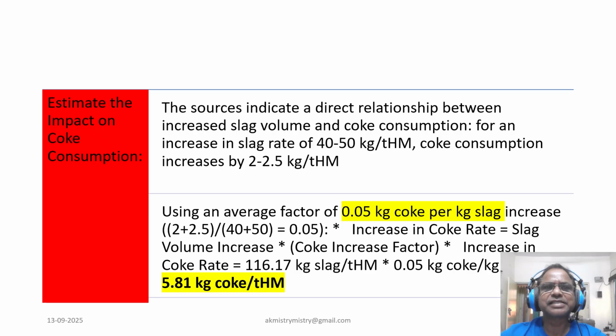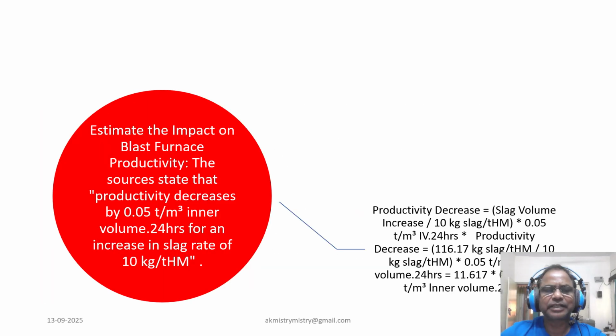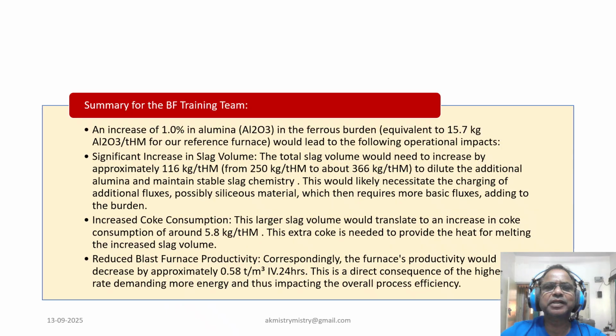And so we can say that productivity suffers hugely. For every 10 kg increase in slag rate, productivity drops by 0.05 tons per cubic meter of inner volume per day. So with the 116 kg more slag, productivity decreased by 0.58, and that is a direct consequence of higher energy demand and slower process kinetics. So the ripple effect we can summarize: with a 1% alumina increase, slag volume increased by 116 kg per ton hot metal, coke consumption increased by 5.8 kg per ton hot metal, and productivity dropped by 0.58 ton per meter cube inner volume.